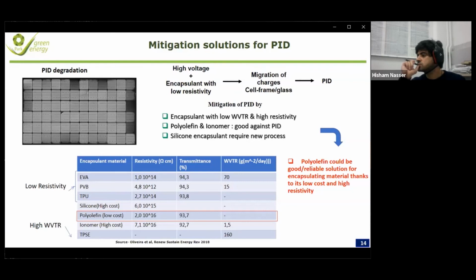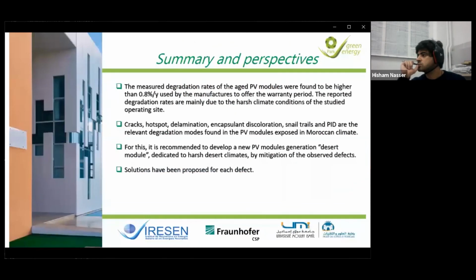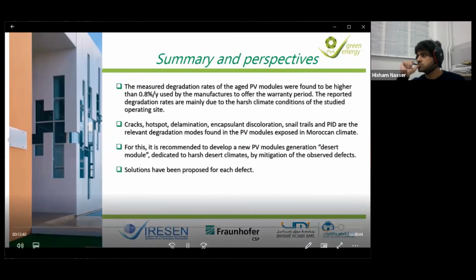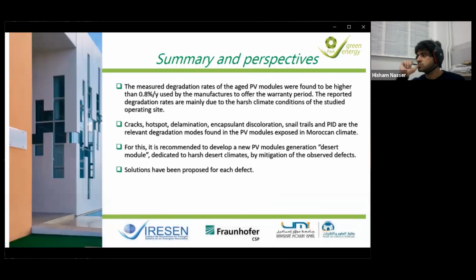So in the present study, polyolefin and ionomer have similar, high resistivity values, but polyolefin has other interesting processing properties since it requires no change to the machine. So in the present study, polyolefin could be a good and reliable solution for encapsulating material thanks to its low cost and high resistivity. Finally, after the inspection of 5 PV systems in the climate of Morocco, we found that the measured degradation rates are higher than that given by the manufacturer, which is 0.8% per year, which is due to the harsh climatic conditions of Morocco.